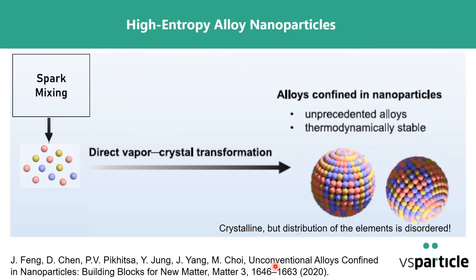A very interesting class of new materials are so-called high entropy alloy nanoparticles. And you see this name of Ji-Cheng Feng occurring here again. Together with the group of Man-Soo Choi in Korea, he used spark mixing to produce nanoparticles that consist of a whole lot of different elements. And these materials are crystalline, but the distribution of the elements is disordered. And that's why they have a high entropy. They have a high degree of disorder, and the high entropy makes them stable. This is a very interesting phenomenon.